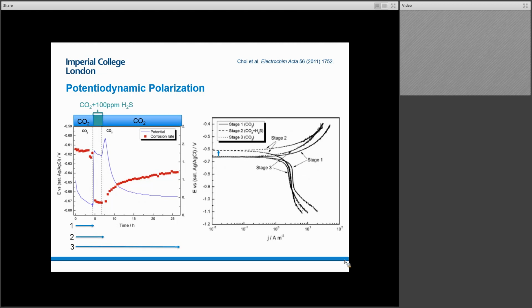When you have this layer, it is interesting because it suggests that the cathodic reaction is not being strongly influenced by the formation of the layer. But by contrast, they suggest that the anodic scan is somewhat more influenced. And as such, we can start to think about the nature of that layer. So if the cathodic reaction is happening, i.e. electron transport is occurring, but we don't believe that the oxidation reaction is happening quite as smoothly, well, that's telling us something about the porosity and the nature of that layer. They assert from literature that this corroborates findings regarding the nature of an iron sulfide layer, particularly sometimes noted as being a semiconductor.